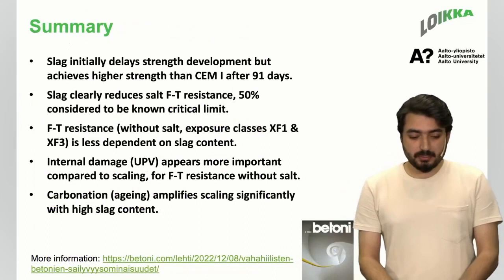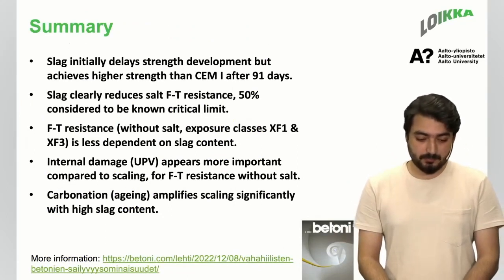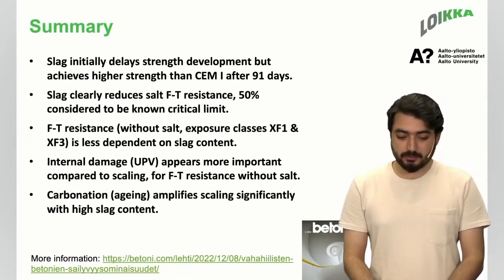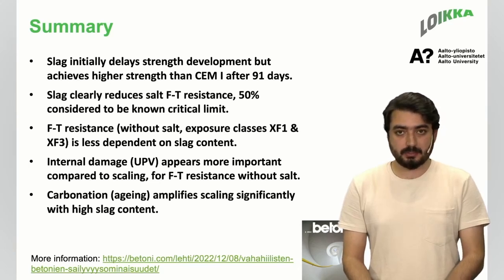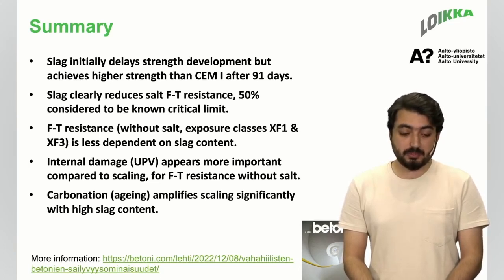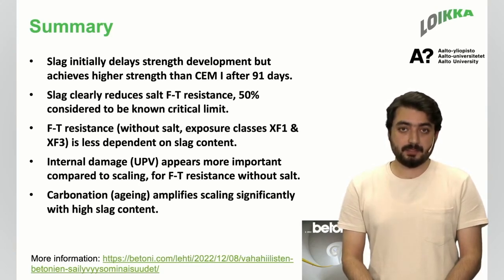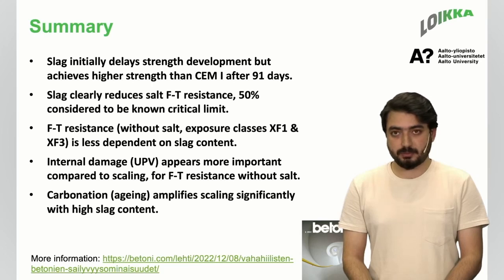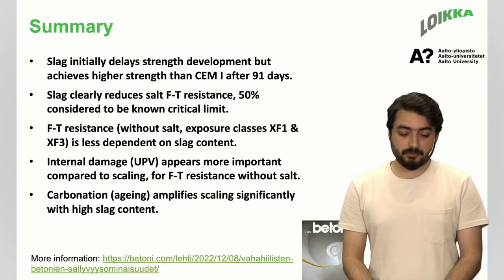So just summarizing all the work that we did. Slag initially delays strength development in concrete, but it also managed to have higher strength than CEM I after 91 days. Slag clearly reduced the freezing and thawing resistance, but we also have a known limit of 50% considered. It's already known, and the testing basically confirmed it.